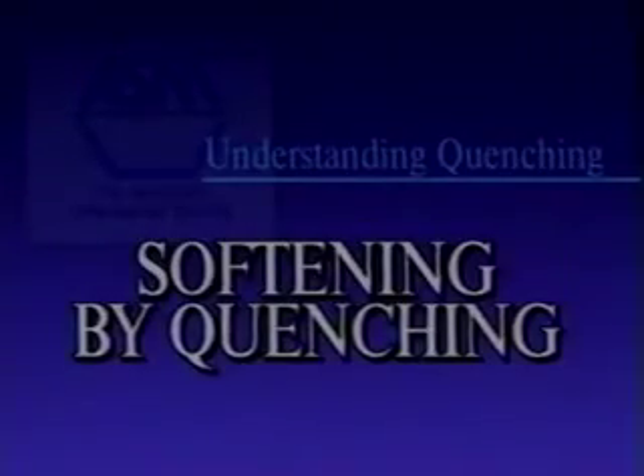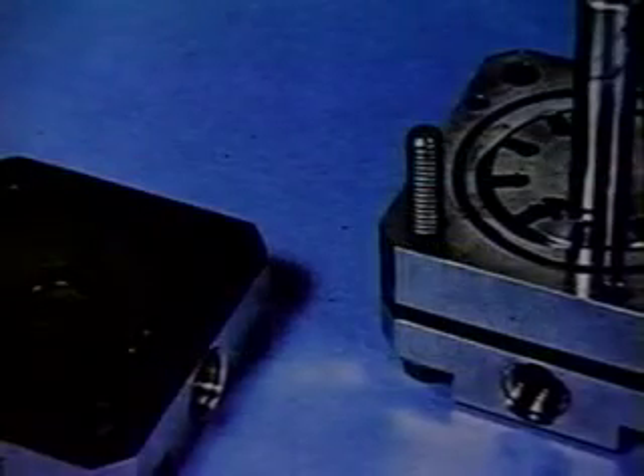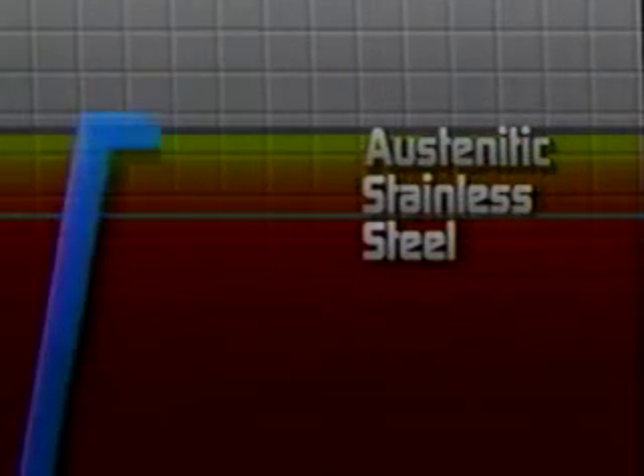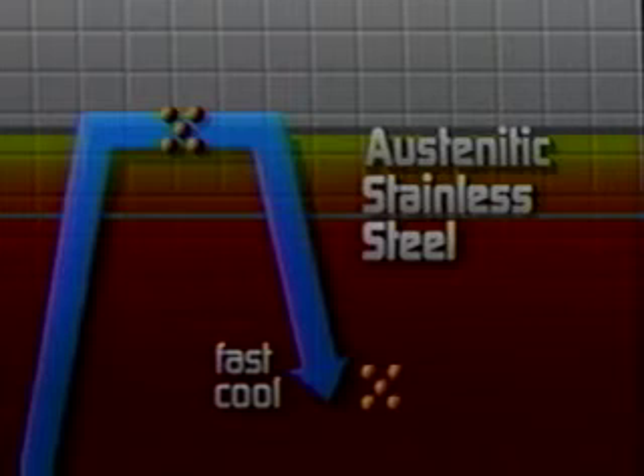Softening by quenching. The difference between austenitic stainless steels and other ferrous alloys like plain carbon steels is that austenitic stainless steels do not go through a phase transformation when heated. Their crystal structure is always austenitic at high temperatures and at low temperatures. The alloying elements in austenitic stainless steels actually increase the range of temperature in which the austenitic structure can exist. However, an austenitic stainless steel can be hardened by working.